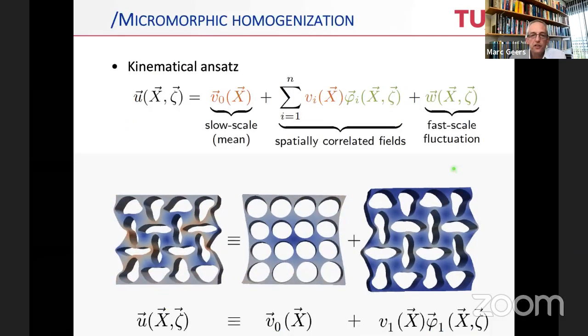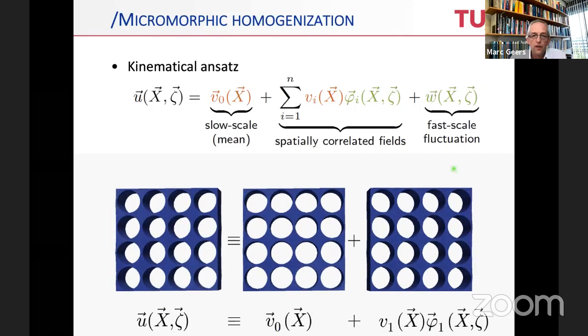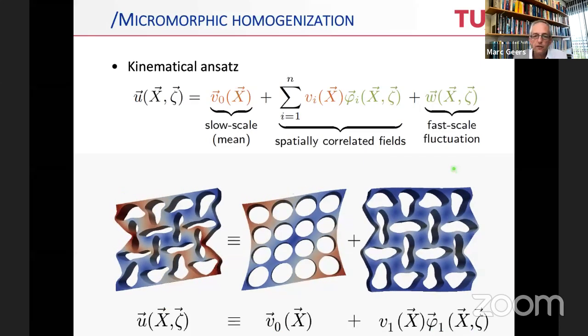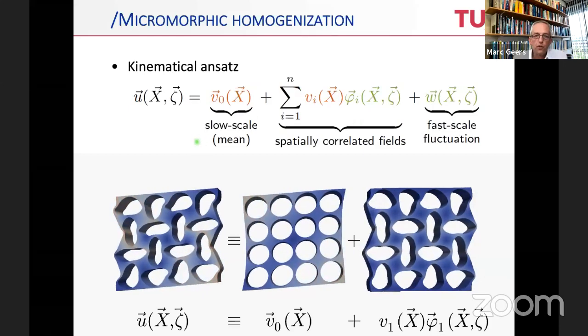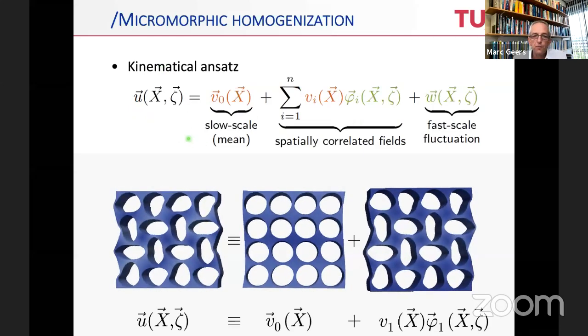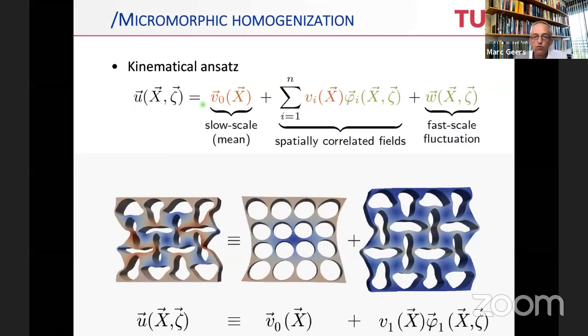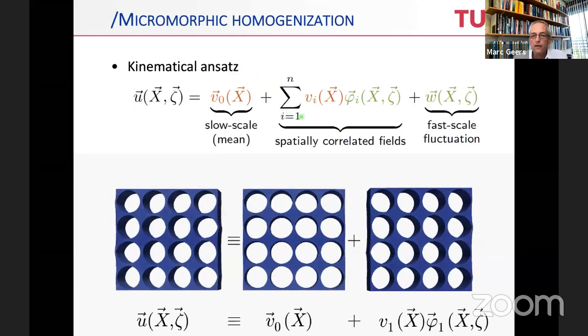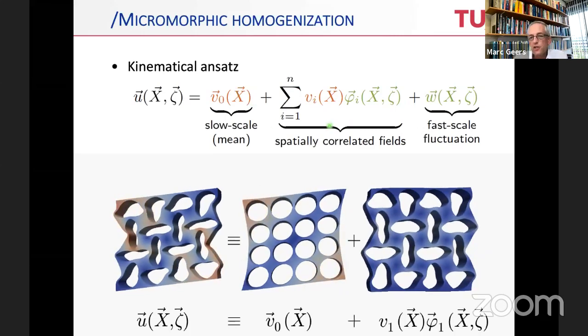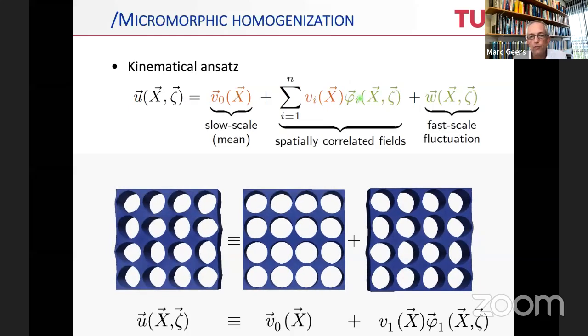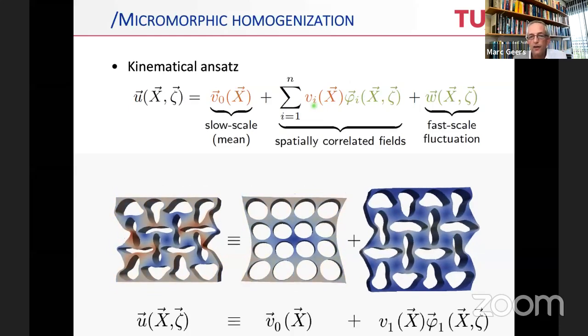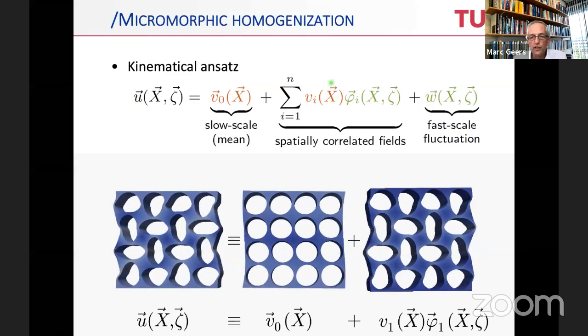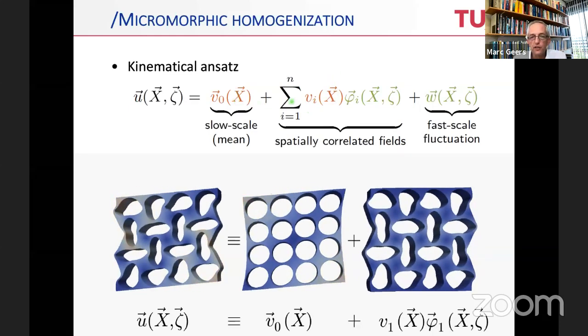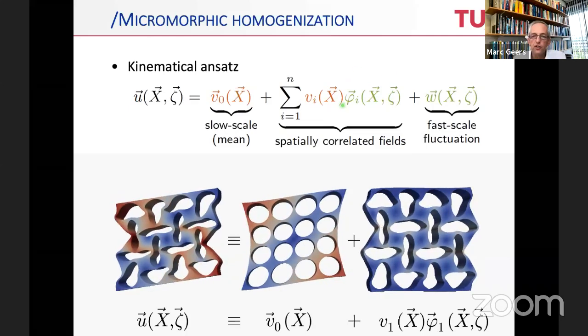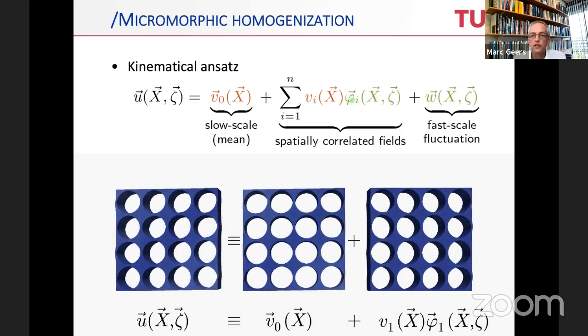And the real trick is actually in the kinematical ansatz that is adopted. It's inspired by what you've seen in the other homogenization frameworks, but what we'll essentially do is split the kinematics into its standard slow scale mean part and the spatially correlated fields. The spatially correlated fields are modes, in this case, for instance, bifurcation modes, times their amplitudes. And these quantities only depend on the slow scales, so that's the big X, whereas the mode itself can fluctuate at a small scale.